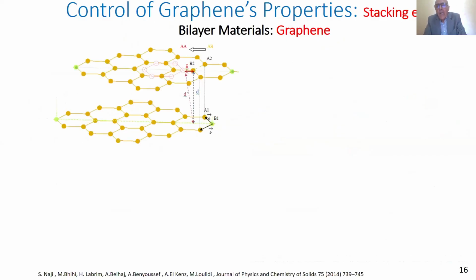The second interesting behavior is the stacking. Stacking may mean how the layers of graphene are stacked for bilayer or trilayer or even for thin films. The natural stacking for graphite is AB stacking. That means that the atom of carbon on the first layer is on the top of the hollow of the second layer, as is shown here. This is the AB stacking.